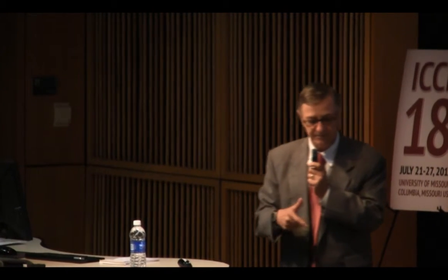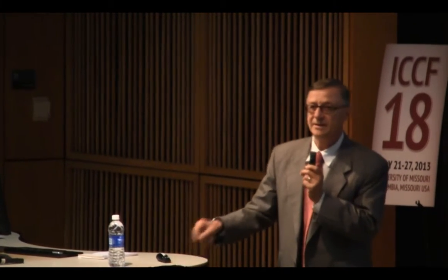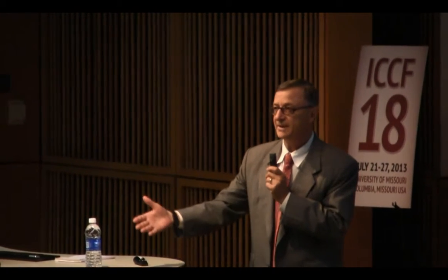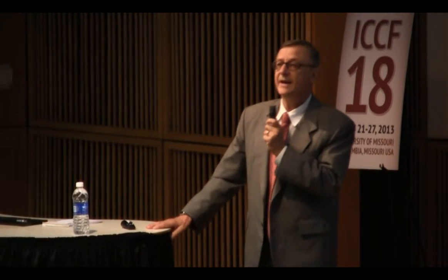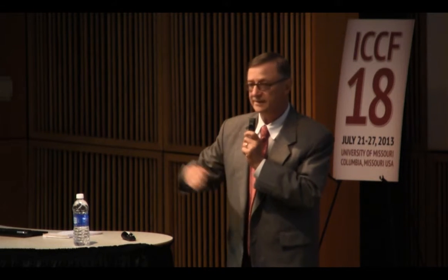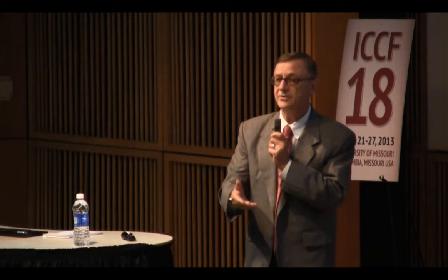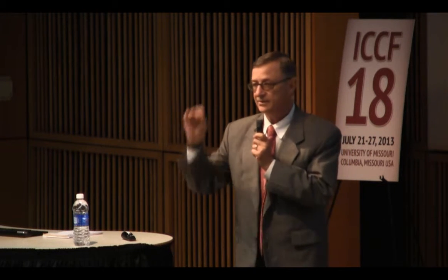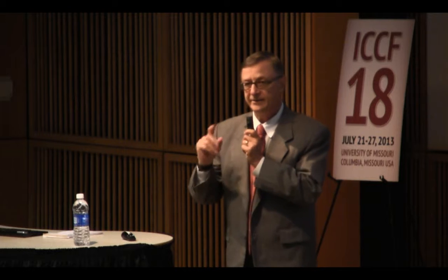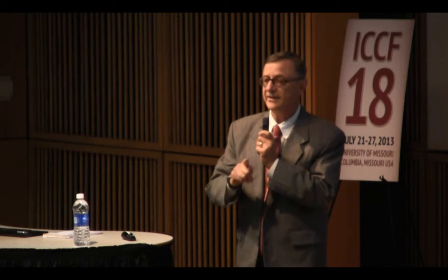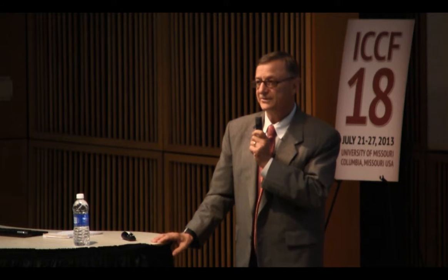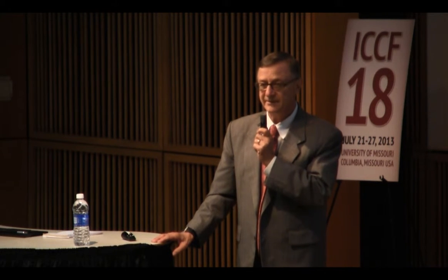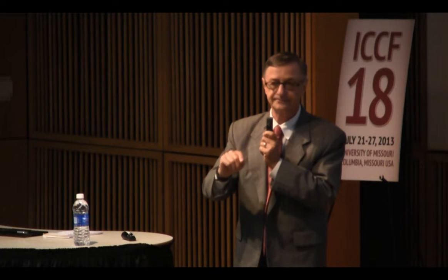But when we started our heat producing program in 2009, we said, well, you have to get control of the palladium metallurgy, right? And so David Kidwell, I remember him being very frustrated. You get this lot of palladium, and you make 10 cathodes, and you do it, what you think is identically every single time, which was the ENEA procedure, where you roll it, you anneal it, you etch it, and you run it. And all 10 cathodes had totally different morphologies, even though you thought you did the same thing every time and the material was from the same lot.